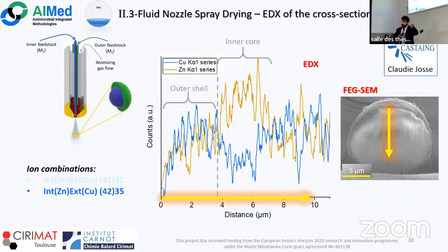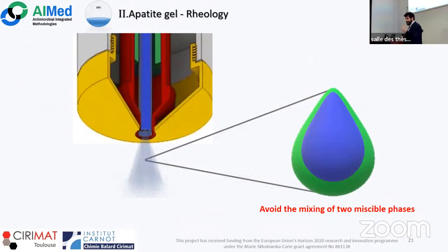The first one is the penetration of the EDX beam, because we have to analyze just the bigger particles, because otherwise we risk having a bulk analysis that's not what we want. And then we lose the sensibility of the technique closer to the sample holder. So we can say the second third of the EDX analysis often is not that reliable. But at that point, we can understand that we can obtain this kind of partial structure, but we have to avoid the mixing of 2 phases that are essentially the same phase, because it changes just an ion in the structure, but for the rest, they are the same. To try to optimize